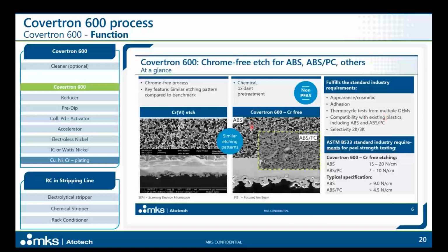And as you can see here in the SEM pictures, again, the pattern is comparable to the benchmark process. But of course, if we use, for instance, one of the standard specifications in the market to check the requirements for peel strength testing, what we can see is that, from a typical specification for the current process, with Covertron 600 we can achieve at least the same values, but our experience is that we can even get higher peel strength values than the benchmark process.